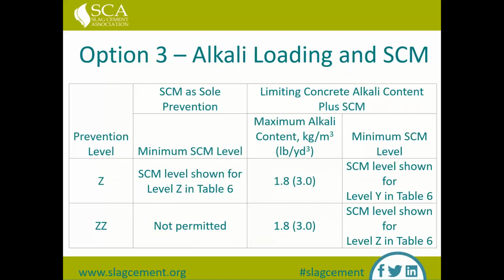This takes us to option 3, where you're looking at both alkali loading and using a prescriptive SCM amount. Again, this is recommended only for the highest prevention levels, Z and double Z. If you're looking at prevention level Z, for example, it lists the alkali loading of 3 pounds per cubic yard, excuse me, that's the maximum for level Y, and also the SCM replacement level for level Y.